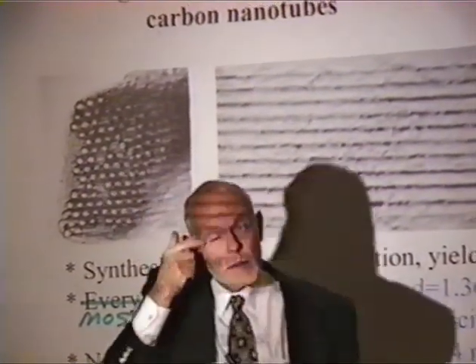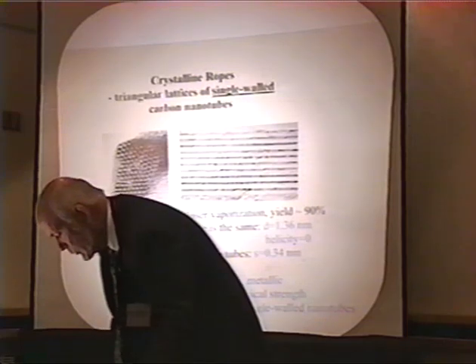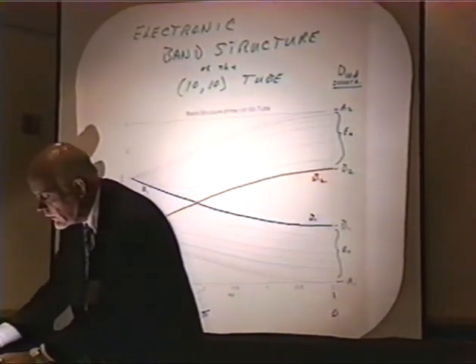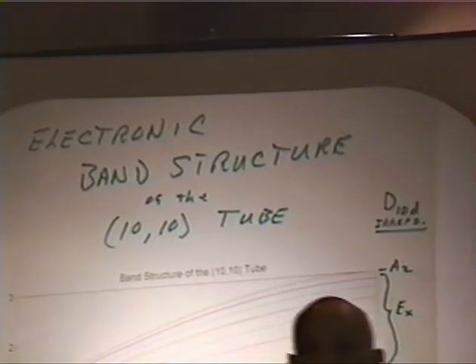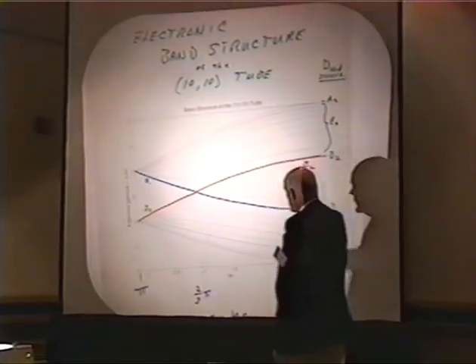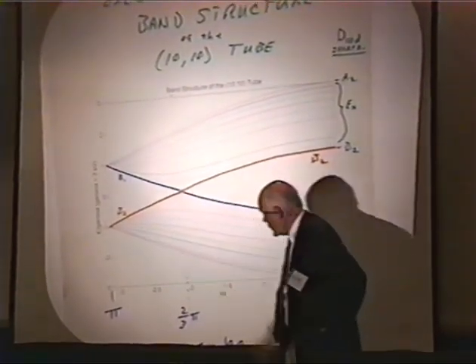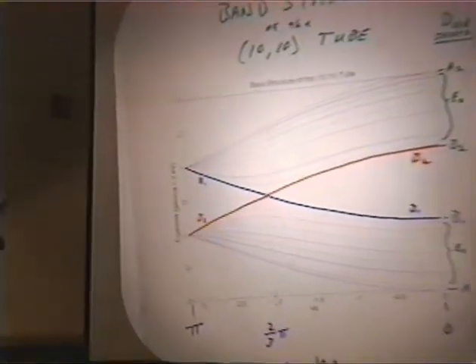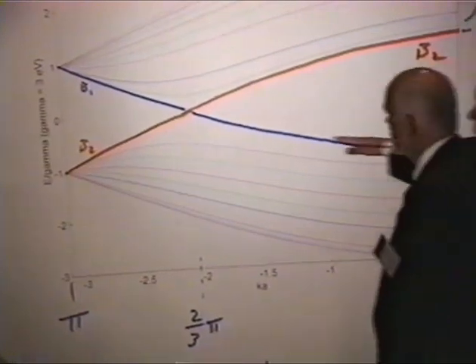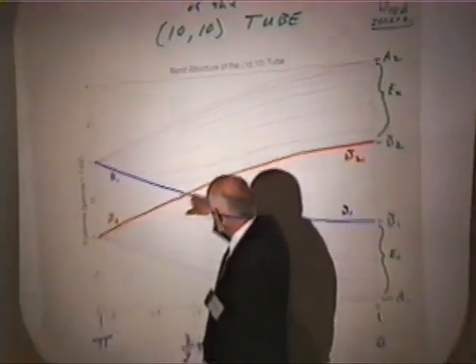And you notice these tubes are arrayed here in a rather crystalline lattice. You notice these lattice plates going through here, and they all seem to be about the same diameters. And it turns out that they are very close to being the same diameter, and there is one tube that appears to be present more than other tubes, and it is in fact this one called a 1010 tube, which has this remarkable band structure. This is the energy of the electronic bands as a function of the wave vector, or the electronic wave function going down the tube. And here are these two bands that cross the Fermi energy here, right in the middle of the Fermi energy. It guarantees this sucker is a true metal.